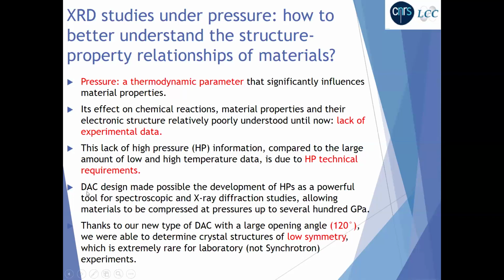It is true that the DAC design made possible the development of high pressure as a powerful tool for spectroscopic and X-ray diffraction studies, allowing materials to be compressed at pressures up to several hundred gigapascal. In our case, thanks to our new type of DAC with a large opening angle, 120 degrees, we were able to determine crystal structures of low symmetry, like triclinic and monoclinic systems, which is quite rare for laboratory experiments.